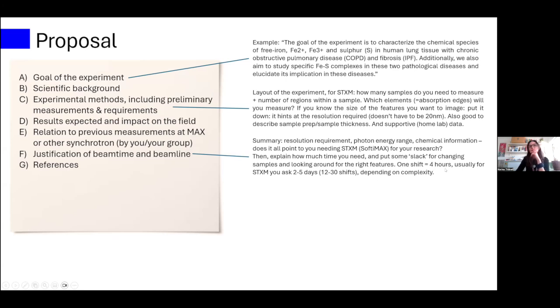So MAX IV is one of the ones that works with one shift being 4 hours, which is unusual. So keep that in mind. And then usually for the STXM, you can ask anywhere between 2 and 5 days, which is the norm. But anything above 6 you would never get. So that's easy. And it depends a little bit on complexity. Mind you, not the amount of samples, because we would just say it's not reasonable if you want to do 100 samples. But this is sort of the thing to aim for.